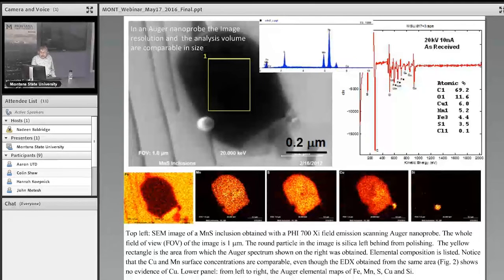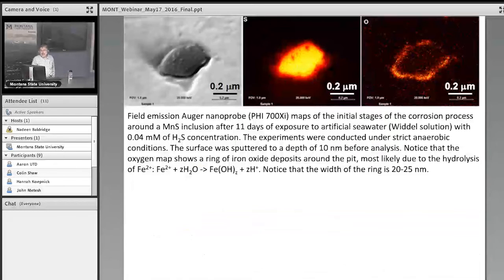Here is the manganese sulfide inclusion. We are essentially at a crime scene. We want to understand how the corrosion is taking place, the elemental steps of the corrosion. This was briefly exposed to a corrosive environment. And here's the manganese sulfide, here's the iron, and we image the sulfur here. In the manganese sulfide, you will see sulfur. You can see sulfur is getting less and less in the immediate surroundings. It's extending into the iron matrix, like a dendritic structure right here.